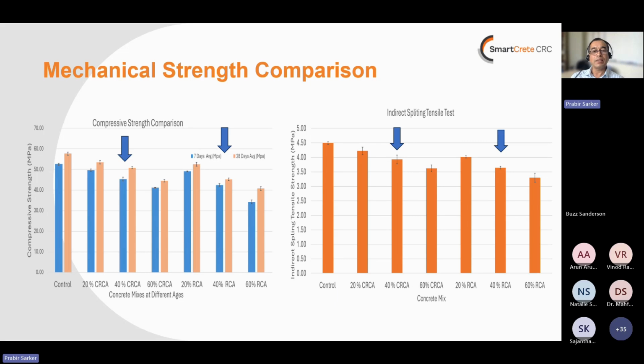Some comparison of the strength using this CRCA. On the left side, we have the compressive strength, and on the right-hand side graphs, we have the comparison of the indirect splitting tensile strength. In each of the graphs, the leftmost two bars are for control concrete using 100% natural aggregate, and then we have 20%, 40%, up to 60% of CRCA, and on the right we have 20%, 40% and 60% recycled C&D waste concrete aggregate. For example, it is about 50 MPa concrete for natural aggregate, and when we used 40% CRCA, we got about 12% strength reduction.